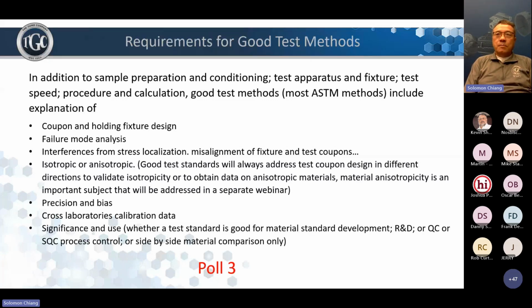The standard test method must provide meaningful results for use and be repeatable intra-laboratory and inter-laboratory. That means if you have the same set of samples and you test it 2 or 3 times, it should provide consistency, the same result within a couple of percent by the same laboratory. And then if you take that material and send it to a different lab, if they follow a good test method, the result should be similar, again, within a few percent.